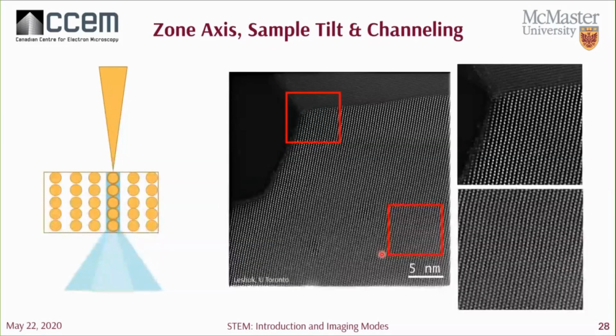Another important thing that you're going to want to think about is the position, or the tilt, of your sample. In acquiring atomic images, it's important to align the crystal so that the zone axis is parallel to the beam. By doing so, we get what we call channeling conditions. This is where the fast negatively charged electrons are attracted to the positive atomic nucleus in the column. And so it channels, it focuses the probe of electrons to exactly where the scattering occurs. By doing so, we get less beam spreading or broadening of your beam as it travels through your sample.